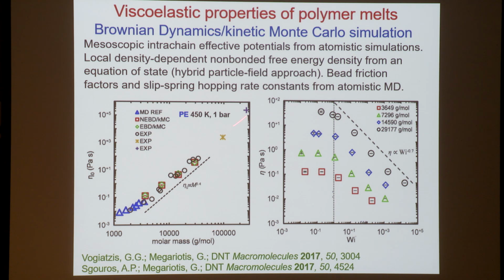This is shown for polyethylene under these melt conditions. We have a set of results from equilibrium Brownian Dynamics kinetic Monte Carlo. These are the red points, and a set of results from non-equilibrium Brownian Dynamics kinetic Monte Carlo of the melt being sheared. The results from the equilibrium and non-equilibrium agree with each other.